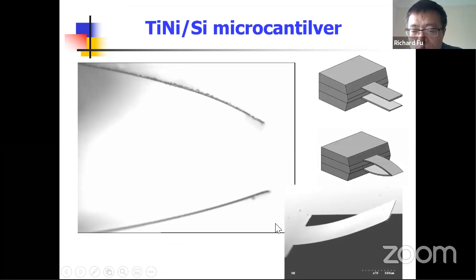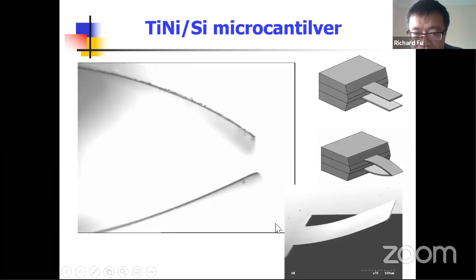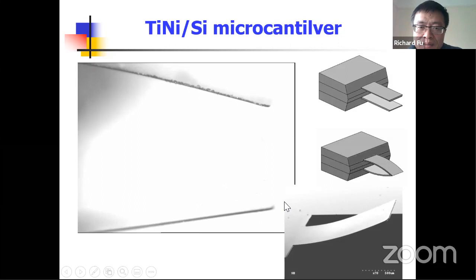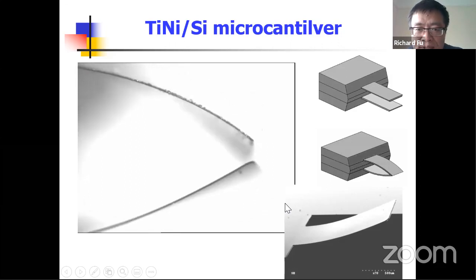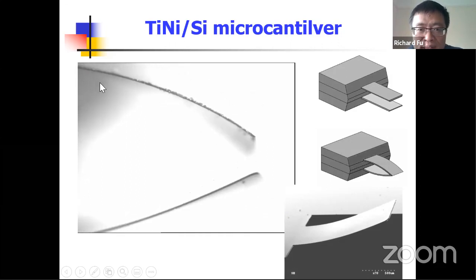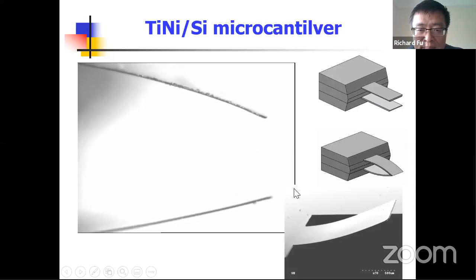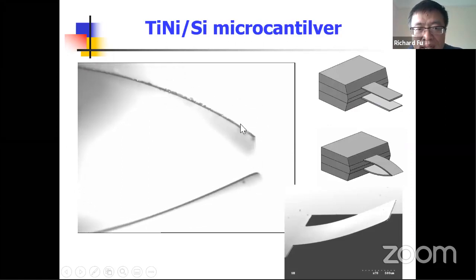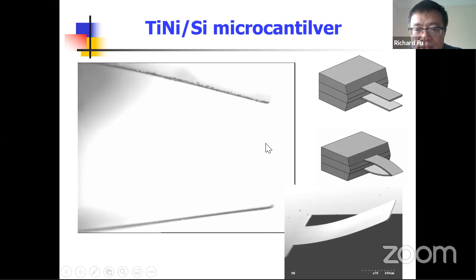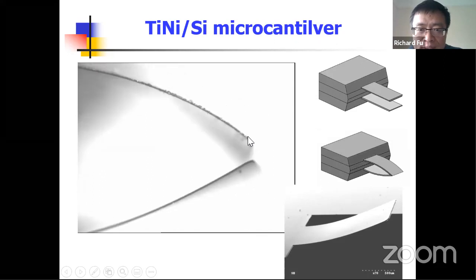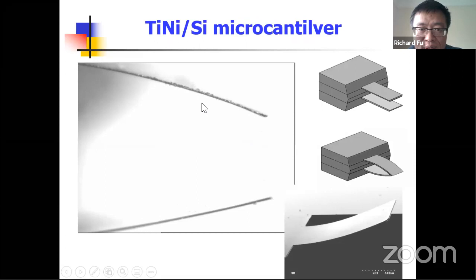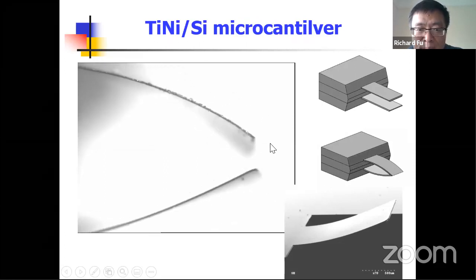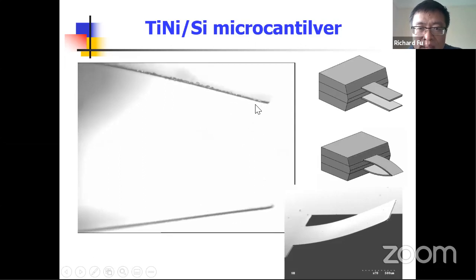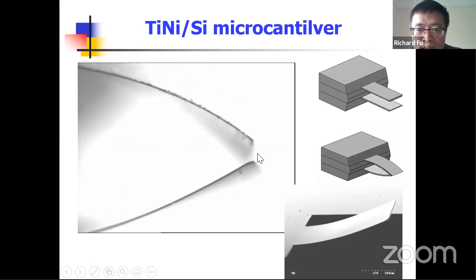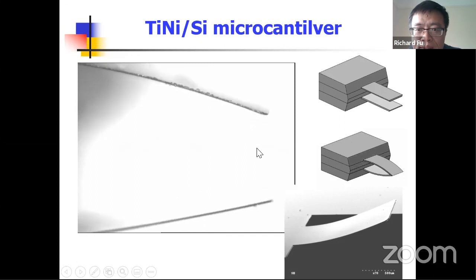The frequency can go up to hundreds of hertz, which is quite useful for some applications. If we can design two cantilevers and put them together, then we can realize the function of a micro gripper. The advantage of titanium nickel is that it has very large force and also very large displacement. So we can open and close with very large force and displacement.